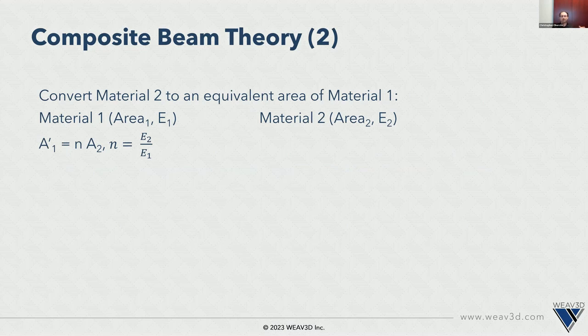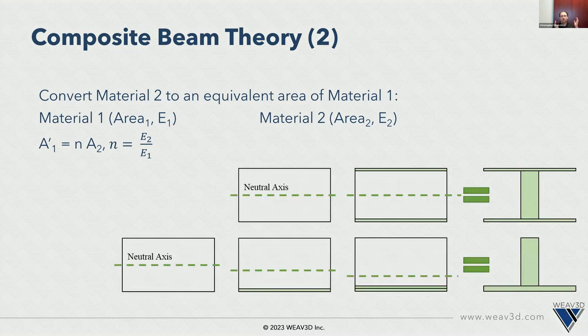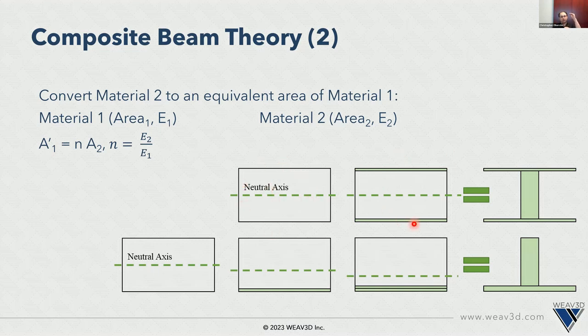The effective cross-section of that material 2 converted into material 1 is the original material's cross-section times the ratio of the modulus. So what this looks like in an effective area calculation, if you were to have a plastics material as your base here, what I'm showing is this neutral axis, the dashed line here. That neutral axis is for the original material. I then add a layer of composite on the top and bottom.